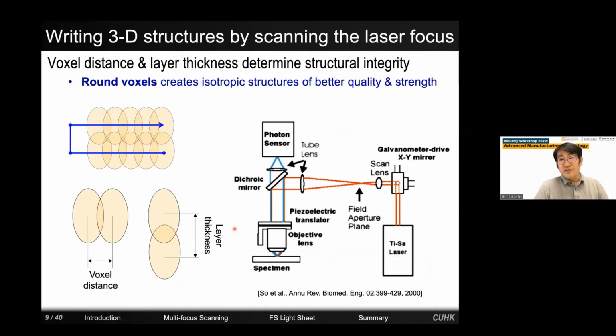So this is what's been done in the past. People pair the femtosecond laser with a pair of scanning mirrors. As a result, by raster scanning the laser focus, voxels can be created in a line-by-line, layer-by-layer fashion. So when one layer is completed, the laser is moved to the second layer by a specimen stage or piezoelectric objective scanner to complete the 3D fabrication process. And this is very slow.